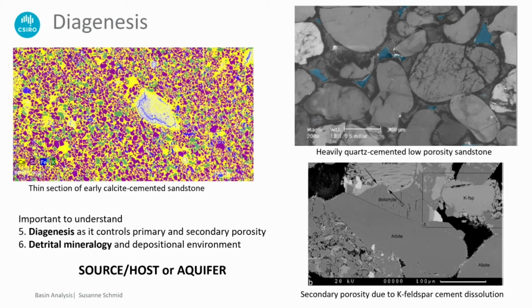Conversely, if you have a clean sandstone, which is quartz arenite or something, a fluvial sandstone, beautiful porosity, usually in hydrocarbon systems, 25% porosity, a perfect gas reservoir. If you bury that and you get into the chemical compaction zone, you're compressing the quartz grains against each other, and that's causing quartz cementation. And the quartz cementation fills up the pores. On that right top picture, you see all the blue stuff, that's the porosity. All the detrital grains are the light gray, and then the cements are the darker gray.